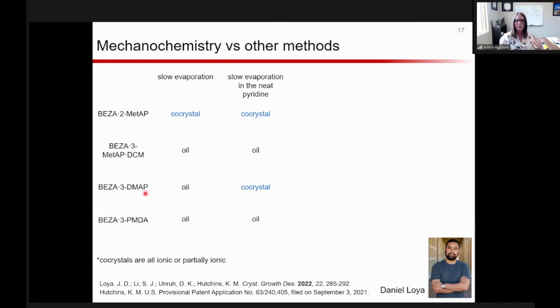So that would not really be ideal, especially if you have precious reagents, to have to use excessive amounts to get it to work versus just stoichiometric. So this does work with a caveat that you have to use excess of the pyridine to get that to work. But in the case of the 3-methyl and 3-PMDA, again, just getting oils out of those experiments.